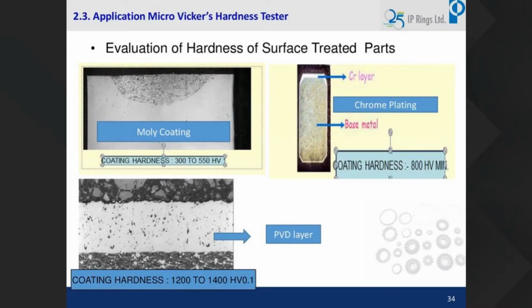Next, as I told you, in the incoming process, in our control plans, after coating it is mandatory for us to check the hardness and the depth of the coating. So we use micro Vickers hardness testers for such inspections. This is a chromium plated ring. The minimum requirement for hard chrome plating is 800 HV. And this is a PVD coated ring, magnified. The requirement of this coating is 1200 to 1400 HV, and of course the moly coating, which is slowly phasing out, is 300 to 550 HV.